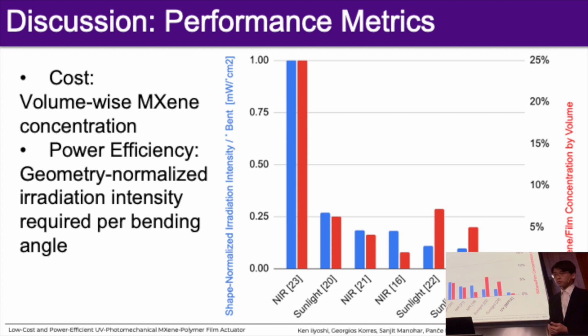And we've also done a comparison with past literature to see that, for this particular concentration, this is a low-cost and power-efficient film. In terms of cost, there is no standard metric for measuring or comparing these films, but we defined it as how much MXene concentration is used in the film. And for power efficiency, we basically defined it as how much bending you can achieve, keeping in mind the shape of the film and how long the bending is.